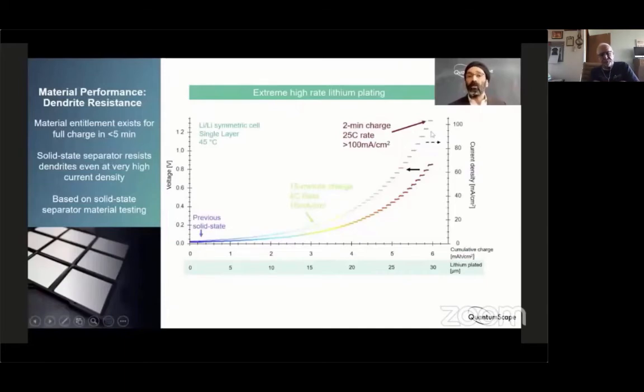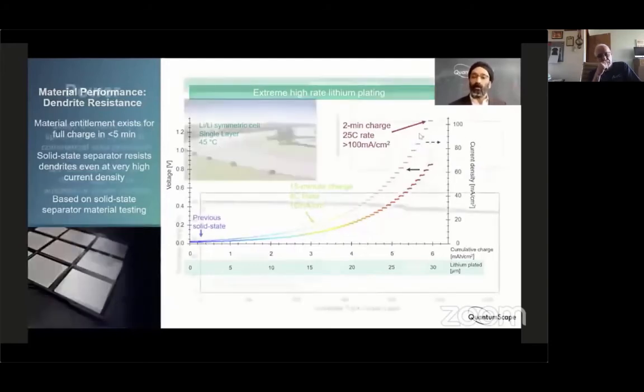This is a really remarkable result. It blows away any previous demonstration in the world of solid-state separators. This was done at a lithium symmetric cell, which is a material level test at 45 degrees Celsius. And you see here that there's a lot of headroom between what the application requirement is for fast charge and the capability of this material.